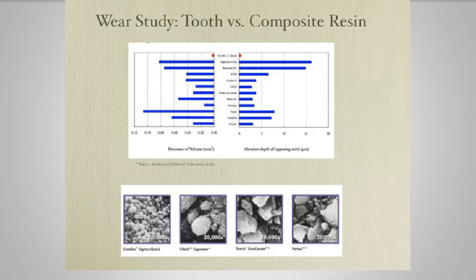And part of the reason is that the filler particles that are used in Sigma Quick are very fine, uniform diameter. In the picture at the bottom you'll be able to see these. They're fine, uniform in diameter. They're considered super nano, which is smaller than a micron and bigger than a nanometer. Now, these fillers are uniform, whereas if you look at the other composites from other manufacturers, you're going to get some irregularity because most of these are hybrids. So what happens in a wear study, especially in wear in the mouth, is you get chipping. When you have larger particles, as you do with some of these other composites, you're going to have larger spots of ditching and larger spots of wear that are going to show more. And that's evident in the study that's being shown there.